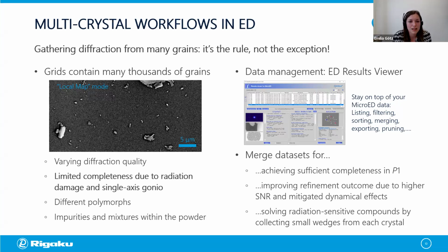Finally, if you have extremely radiation sensitive crystals, one strategy to cope with it is to collect only small wedges of reciprocal space from each crystal and then merge them together. Another possibility would, of course, be to use cryotransfer and measure the sample at 100 Kelvin, which can also be done.